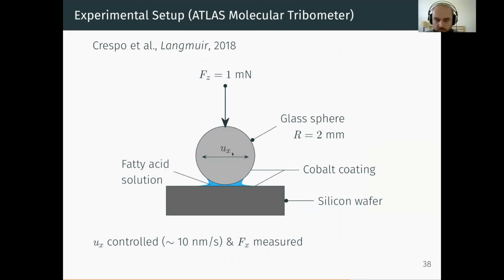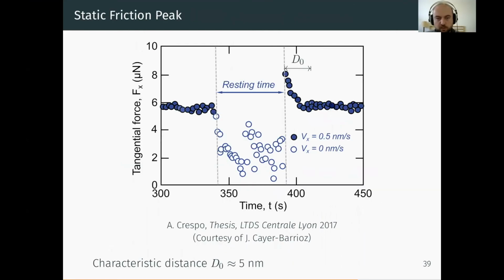of those fatty acid coatings. So what they have is a glass sphere that sits on top of a flat surface. They have a solution at the interface. They control the sliding velocity and they measure the friction force. One of the things they observe, which I think is really interesting, is an aging phenomenon. What they do in the experiments is that they slide, they measure friction force, they stop sliding and they measure the force that relaxes to a non-zero value.